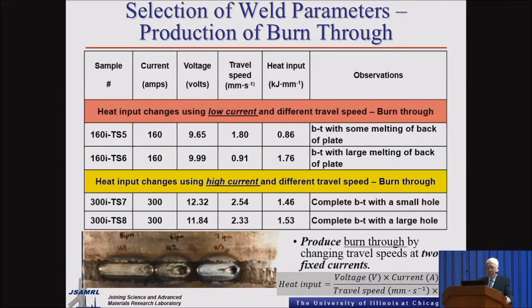Now the other one has to do with the changes in the production of the burn through. In the case of the production of burn through, we use a low current and a high current. And again, the only thing that we did here is change the travel speed, and that will produce very high heat inputs. You can see we have burn through with some melting of the back plate for the low currents. In the case of the high currents, we actually see some holes being formed.